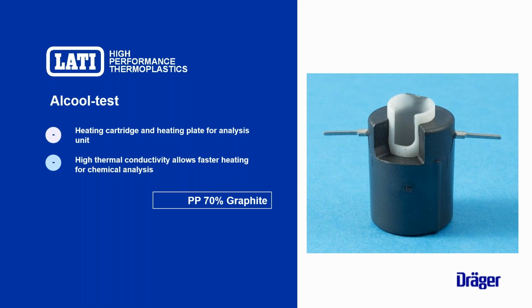thermal dissipator, but also as a resistor. So applying a differential voltage, by Joule effect, it will heat up, and then the heat will be spread towards the inner part of this component, where the sample holder is placed, to analyze the sample.